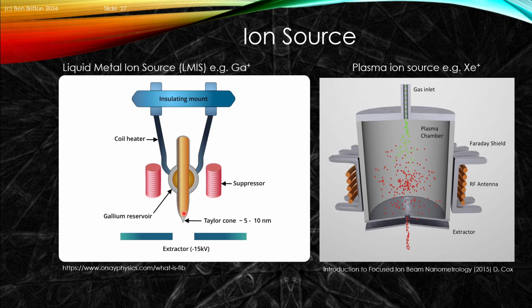It forms a small, very sharp so-called Taylor cone, and as the ions are extracted by applying a high voltage through the extractor voltage here, they are pulled off the surface of the Taylor cone. Very similar to how we would effectively exploit the work function of our tungsten filaments to enable us to operate our tungsten SEM. We can do very similar. But the key trick here is that this wet source enables that once the ions have been removed from the Taylor cone, then new gallium can wet and drop down and form a new cone. And by controlling the operation of the extractor and the suppressor, we can get a stable tip that will last us many hundreds of hours before changing the tip of our system. So that's the liquid metal ion source.